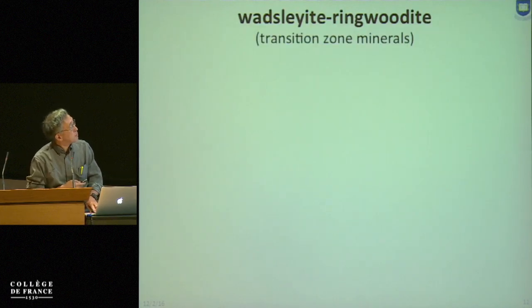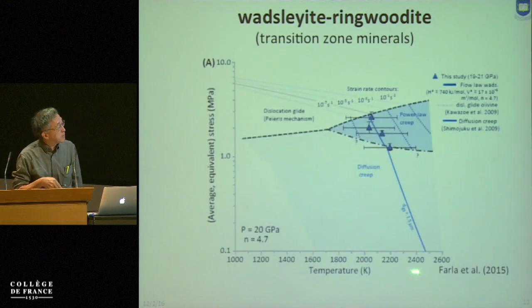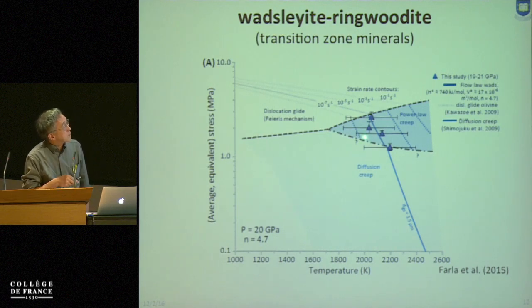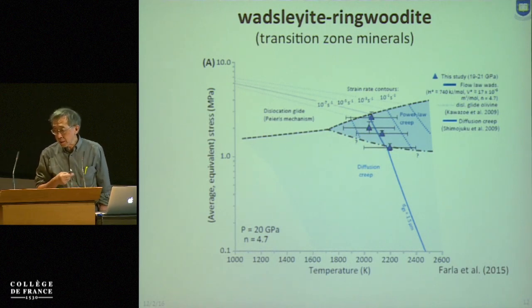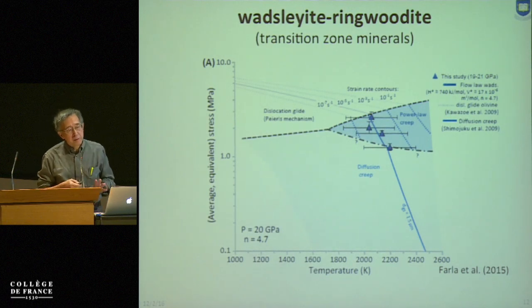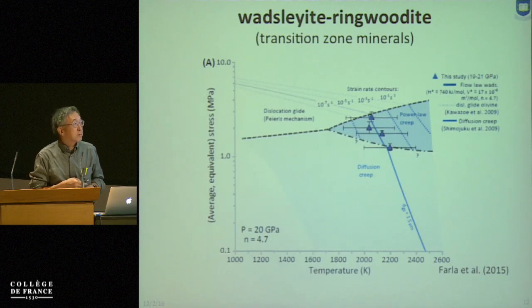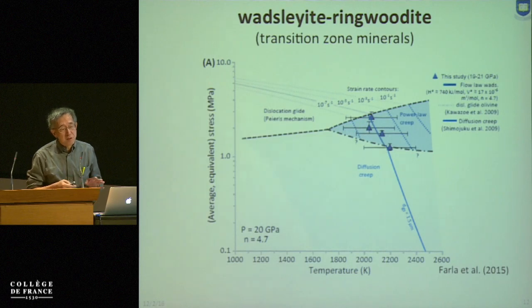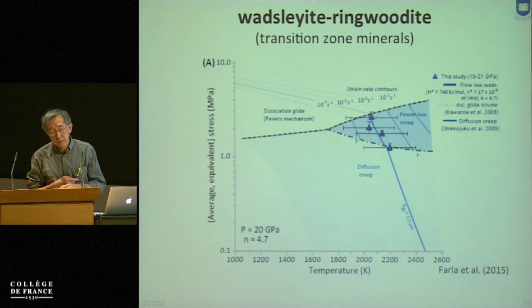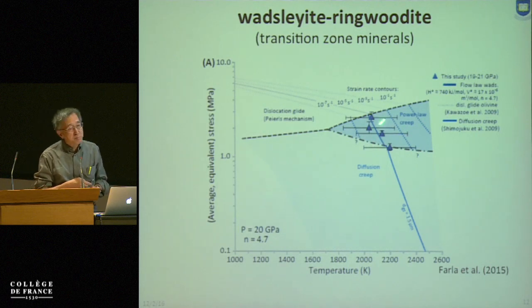And we also performed various experiments on the transition zone minerals. This is a paper by Robert Farla et al., published last year. We collected lots of data, the rheological data as well as microstructure observations. And then we came up with the inferred deformation regimes corresponding to our experimental conditions. Those are over here, plotted against a roughly estimated deformation mechanism map. The conclusion from this work, based on other work in my lab also, is that the deformation conditions in typical laboratory experiments are sometimes in the high temperature dislocation creep regime, and if grain size is small, sometimes they go to the diffusion creep regime, and if the temperature is low, you may go to the Peierls regime. So the conditions are so close to the mechanism boundaries that you must pay very careful attention when analyzing the data to come up with a flow law.